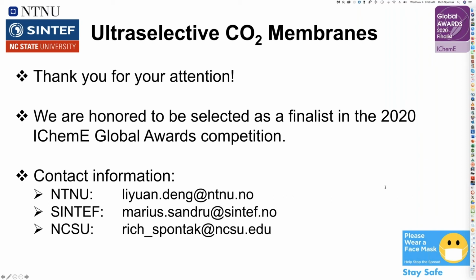where we could actually use the high solubility of CO2 in the ionic liquid in conjunction with that of the water that was present in the channels to help drive the preferred permeability of CO2 relative to other gases. And I didn't show it here, but we did look at other gases. So we did look not just at nitrogen, but also helium and methane. And so we saw the same effect that we saw with CO2 relative to nitrogen, that there was significant selectivity enhancement in that sweet spot at intermediate levels of ionic liquid and relative humidity. I hope that answered the question.